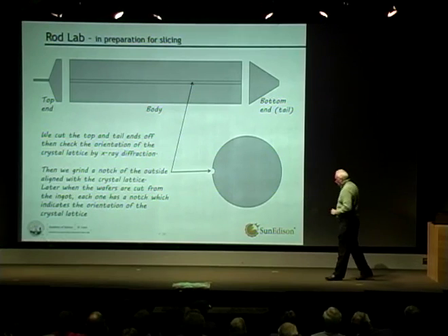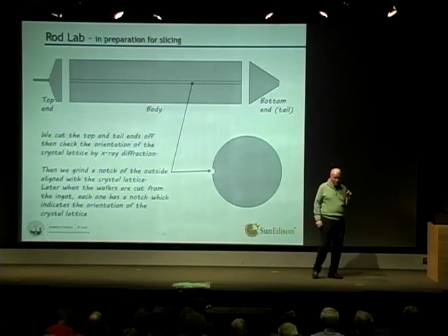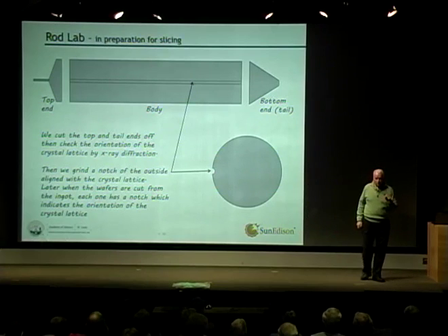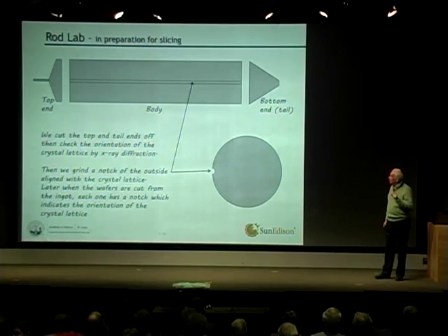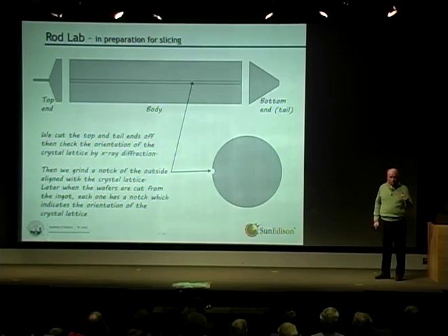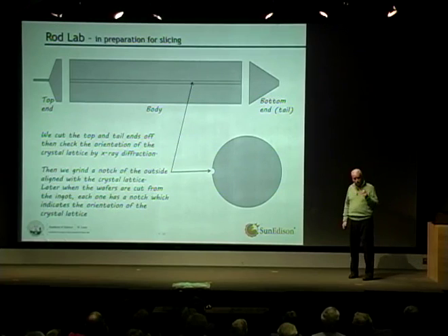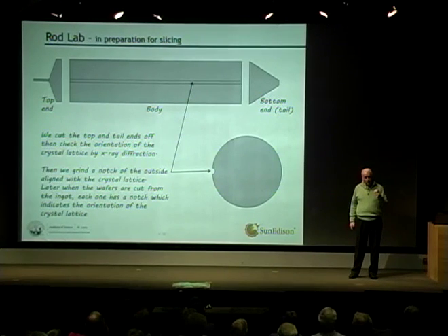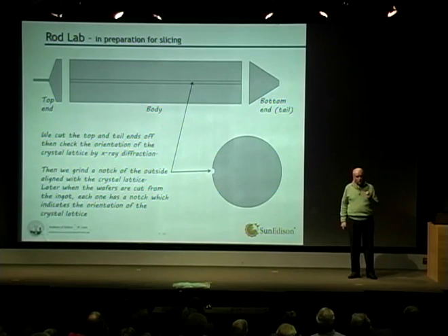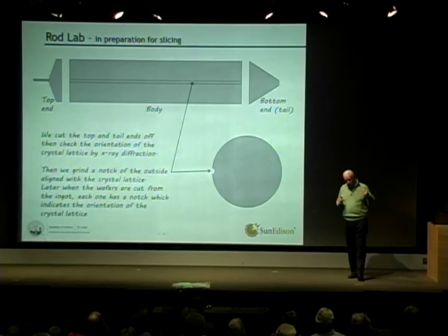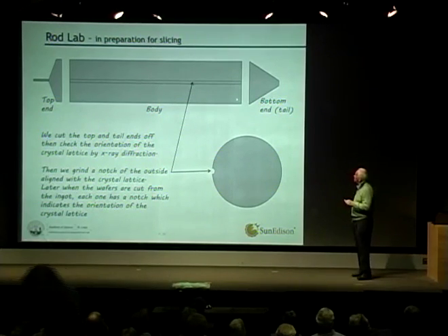Very good question again. And there's a couple of things. First of all, to say it does actually contaminate a little bit, but it doesn't matter too much, and I'll explain why. We actually use diamond grinding wheels. Diamond is carbon, so carbon doesn't go very far into silicon. It doesn't have a high diffusion coefficient. But the matrix that the diamond is held in on the wheel, you also have to be careful. If you use resin bonded wheels, then you can have a pretty clean grinding operation. If you were to use nickel bonded wheels, then you would get more contamination.